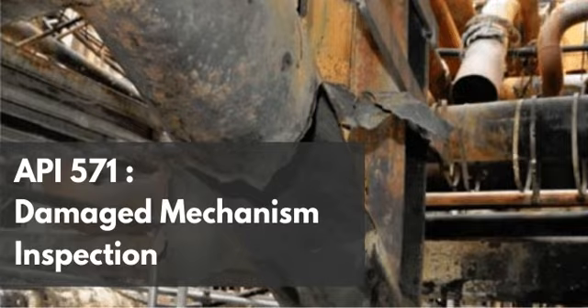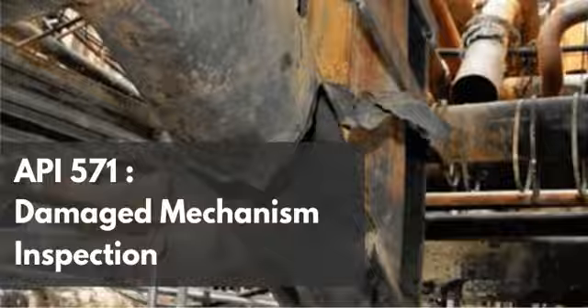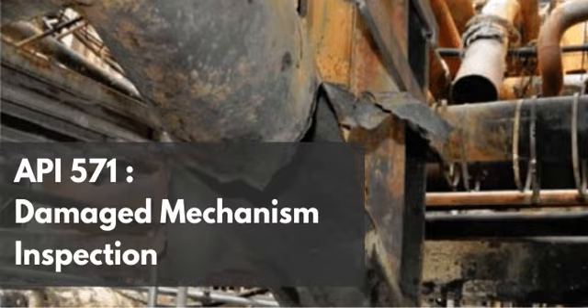Right. So if an inspector uses a heavy, rigid grinding disc and applies too much pressure to remove the hard scale, the sheer mechanical force of the disc will peen and smear the surface layer of the steel. It induces localized plastic deformation. Precisely. You are plastically flowing the metal right over the mouth of the crack. You essentially caulk the crack shut with a microscopic layer of smeared steel. And once that crack mouth is bridged by continuous metal, the magnetic flux lines will no longer leak out of the surface, and the eddy currents will flow smoothly across the smeared bridge without having to detour around the root of the crack. Wow, you have effectively hidden the crack from the NDT instruments. The crack is still there, still propagating under the surface, but the inspector's screen will just show clean metal.